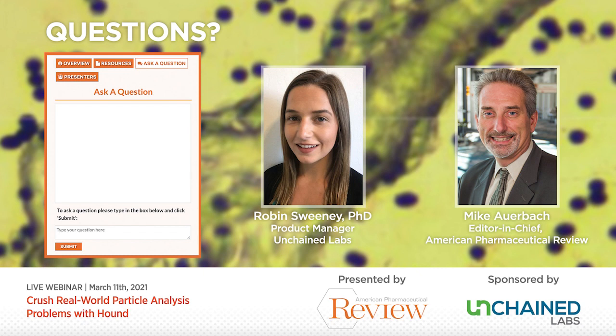In fact, you can use all three different lasers that are on Hound on the same particle. So if you have a true unknown, typically what you'll do is that red 785 nanometer Raman laser, that's a good catch-all, you'll do first. Then you'll move on to the higher powered 532 nanometer Raman laser, and finally LIBS in that order to get the most information possible from one particle.